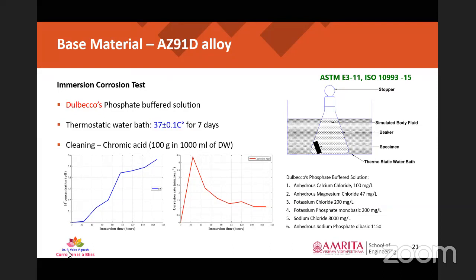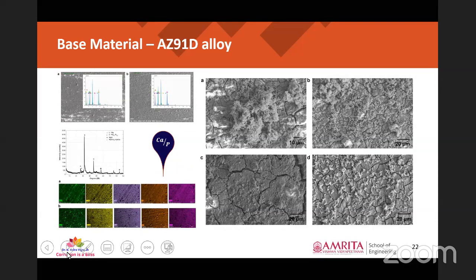Okay, so we thought of understanding the corrosion mechanism present in the material. So we did some EDS, SEM, and XRD based analysis. Initially, after the first day of immersion, we observed a cracked surface which widened with immersion time in the magnesium alloy, that is a normal magnesium alloy. Added to that, we observed flower-like clusters that bloomed over the surface of the specimen with increase in immersion time.